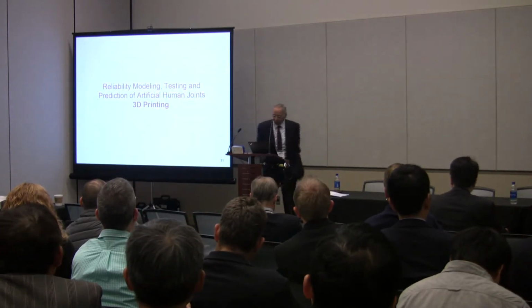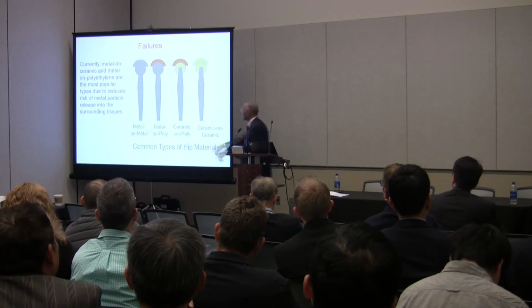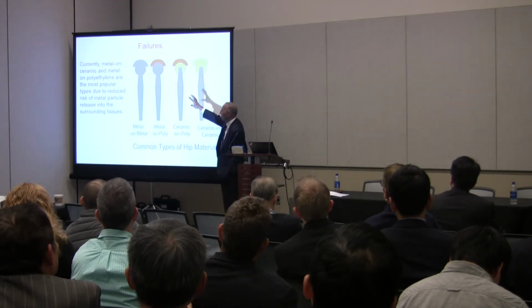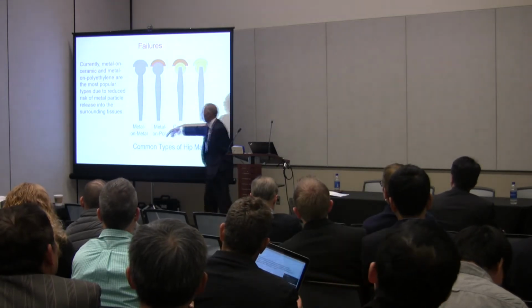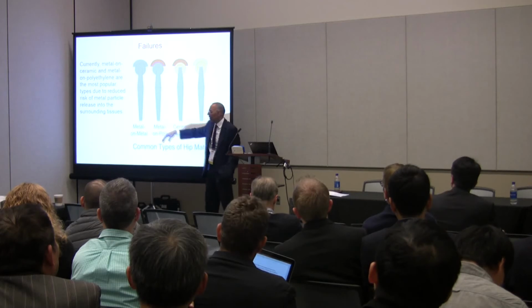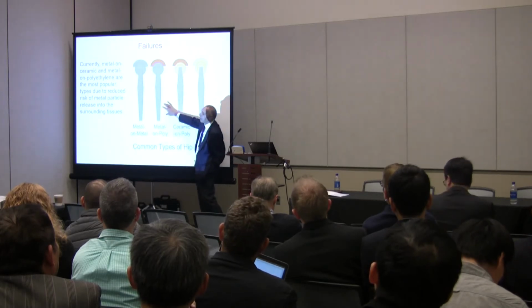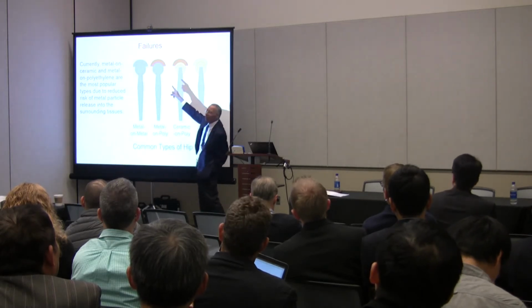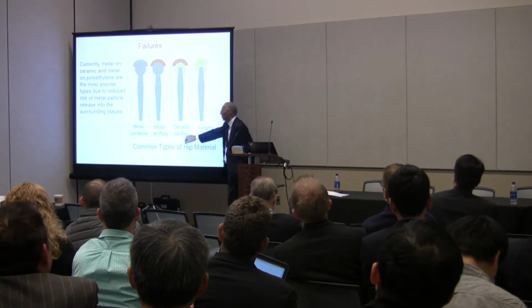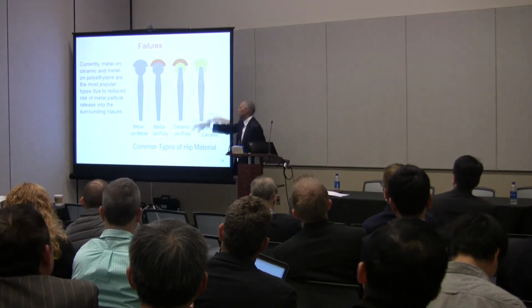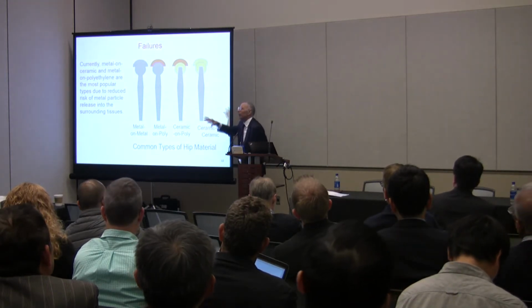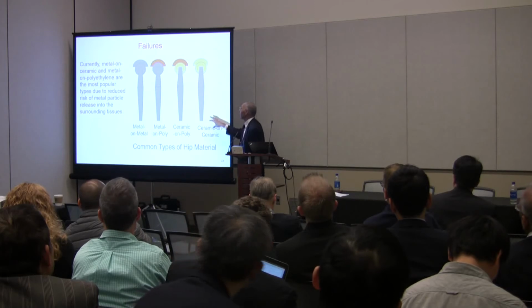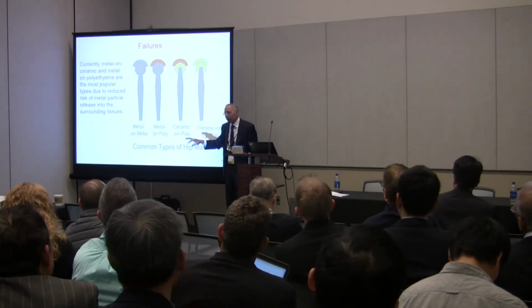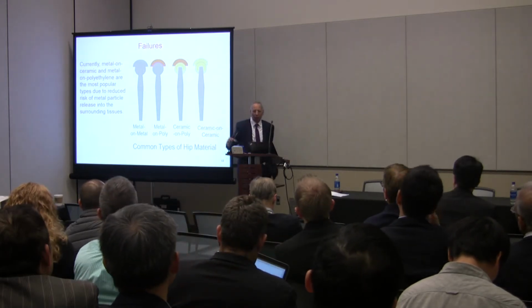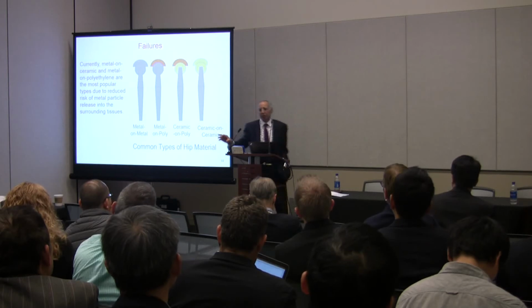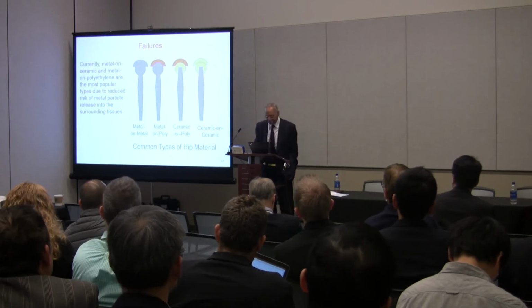So if you look at what the joints we have, these are typical joints. This is currently available in the market. Metal on metal, perhaps the worst. And metal on poly is okay, except you have a wear out in polymer. We have ceramics in poly. This is better than just metal in poly. Less wear out. And ceramic in ceramic, it is really no wear out, but the fracture when you fall due to brittleness of the ceramics is the problem.